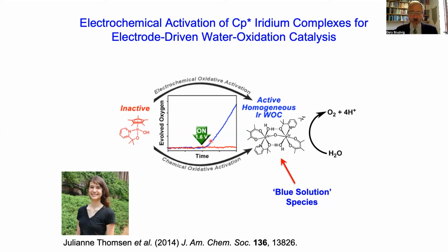And you can see very fast oxygen evolution in the case of the activated species, this blue solution species, and essentially no oxygen evolution for this precatalyst, although we have shown that this is in fact a water oxidation catalyst. It's just that it's so much slower than this dinuclear complex that it doesn't show up on this trace.